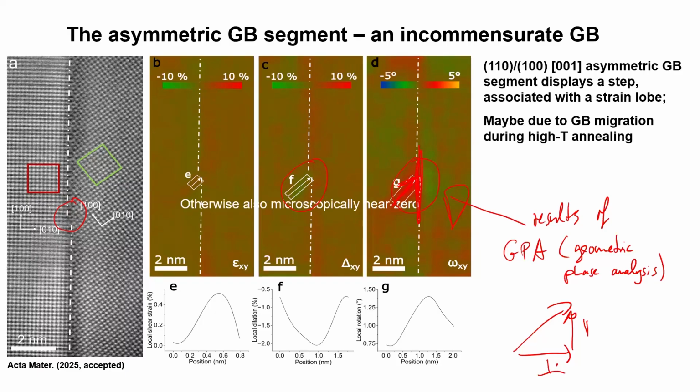There is a resulting force acting along the boundary plane. This is something which we don't understand, which the modeling doesn't understand so far, but it would be very, very important for the diffusive processes. You would normally think of mechanical equilibrium, so when you do these calculations, you always calculate mechanical equilibrium. So in total, the material is force-free and local forces counterbalance each other, right?